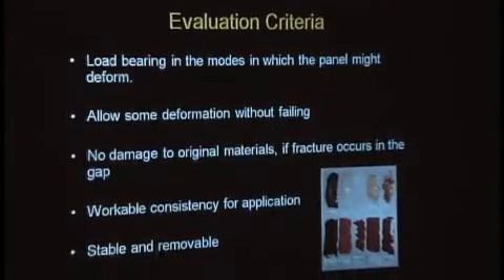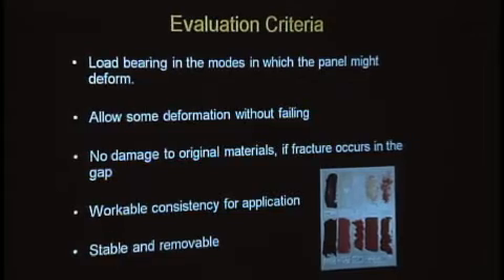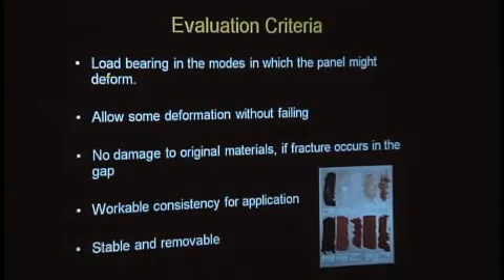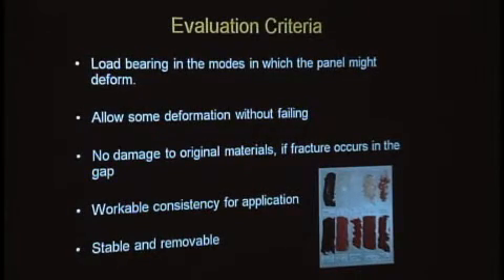So the criterion for me for this work was that the test we did would look at the painting and the gap filler in the mode in which it was actually going to be in reality, rather than in some artificial situation. So I was interested in its load-bearing properties and the modes in which it would be in the panel as it deformed, allowing for some deformation without failing within the gap filler, so that no damage should happen to the original materials of the painting if fracture occurred in the gap. Obviously, a workable consistency was essential, stable and removable.